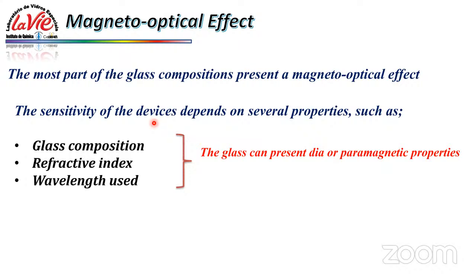Most of the glass compositions that we can find in the literature or even in the market present a magneto-optical effect that may not be very sensitive, but some of the glasses can reach a relatively high sensitivity. The sensitivity of the device depends on several properties. We can work on the glass composition, for example. Changing the glass composition, we can change the refractive index of the material, and it is also related to the increase of the Verdet constant.